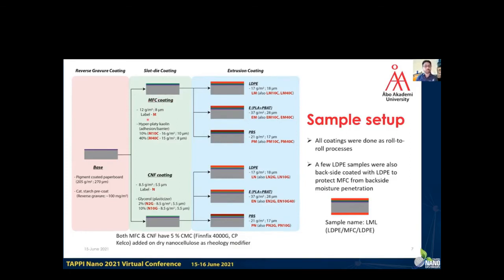And we wanted to see the influence of pigments on barrier properties. So we added hyperplaty kaolin into MFC and produced two additional coatings at 10% and 40% clay addition levels. They're labeled as M10C and M40C, with similar thicknesses.